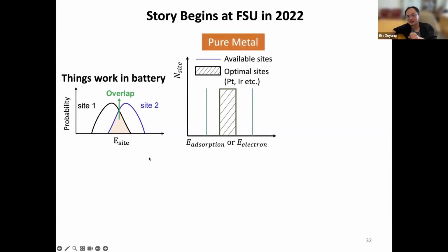Okay, so now we start to talk a little bit about electronic structure, but not electron transport. Because one fact for catalysis is that we're looking for optimum surface sites that have the right electronic structure, because that's going to contribute to the right hybridization with molecules. And that's going to contribute to the adsorption energy we're talking about. And naturally goes to the overpotential of using them in a catalytic reaction. The fact is that sometimes we have to stick with noble metal. And the reason is kind of similar, because noble metal just has the right electronic structure, for instance, d-band center, or for instance, other features of the shape of the density of states. And if you use cheap metal, it just doesn't want to go there,